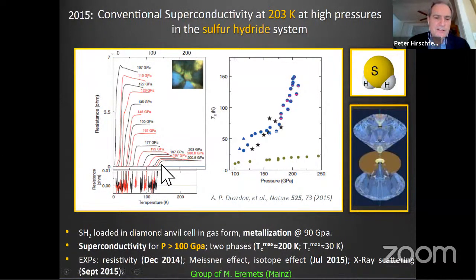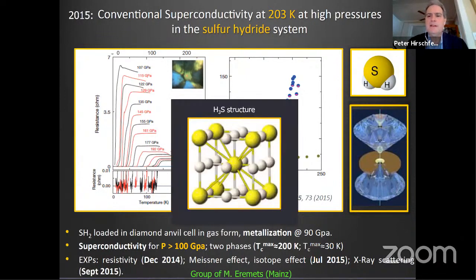This is the resistance you can see. I don't somehow have the plot that shows the resistance at 200 Kelvin, but there is one in the paper. I don't know why I didn't select that one. Anyway, this is what happened in the course of the experiment. The H2S gas first formed a hydrogen sulfide solid compound and then underwent a phase transformation at higher pressures to H3S, expelling some sulfur in the process. And so that was the atomic structure, which gave rise to the correct electronic structure or band structure to support high temperature superconductivity. And unfortunately, it's not stable when you release the pressure. H3S goes away and H2S goes away.